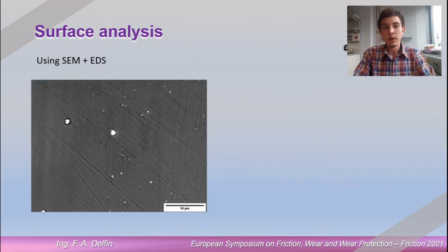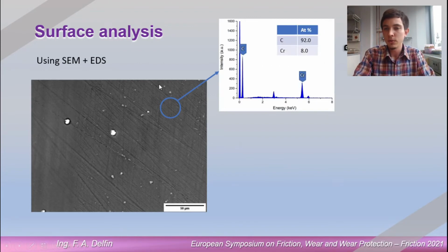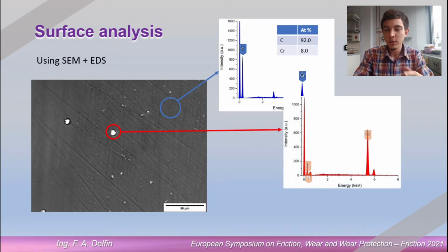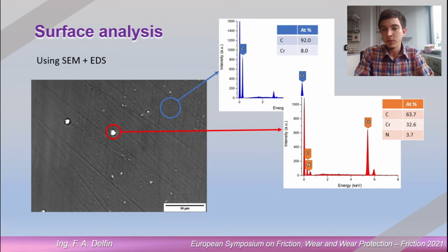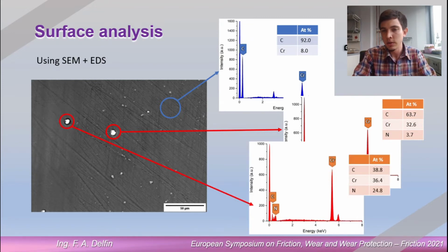Here we have an analysis of the surface using the SEM with EDS. If we see some random part of the surface, with EDS we got the signals of the carbon, of course, the most, and the chromium the least because it's the doping. But we also see this kind of defects, bubbles or drops or whatever you want to call them, around 5 to 10 micrometers in diameter. They are some precipitates of chromium compounds that are made during the process because apparently it's not as clean as it should be to deposit the DLC on top. But we haven't seen any problem regarding this, but they exist.